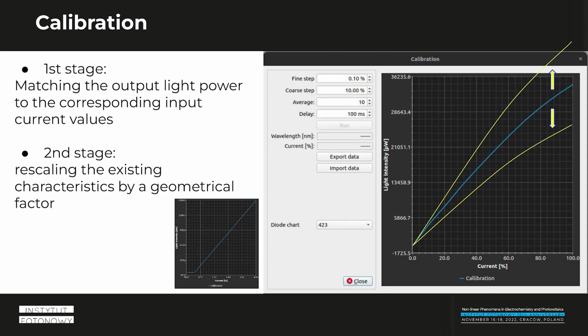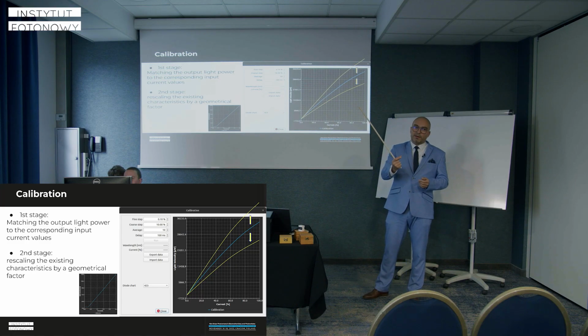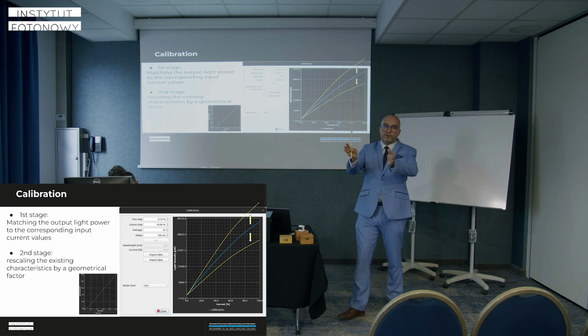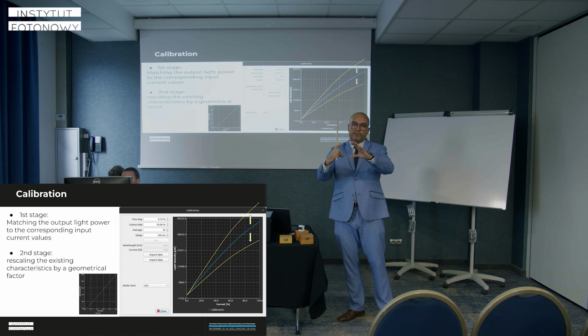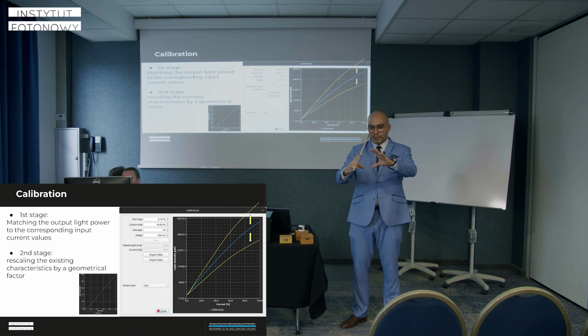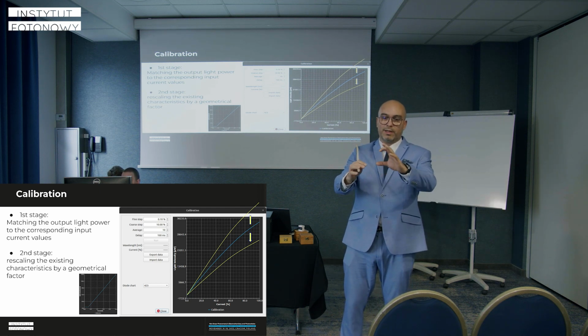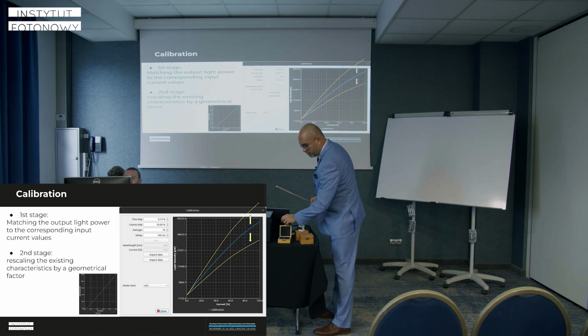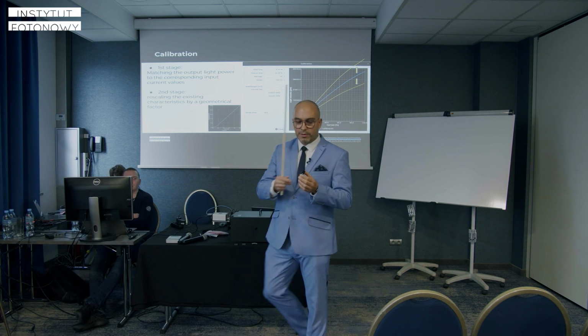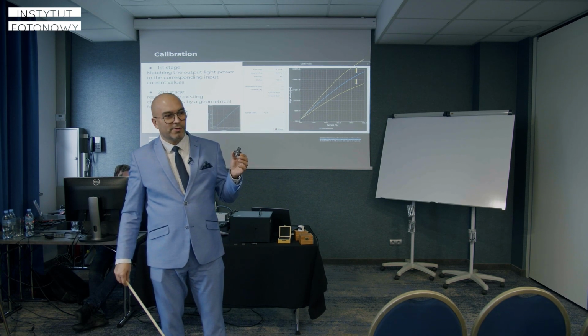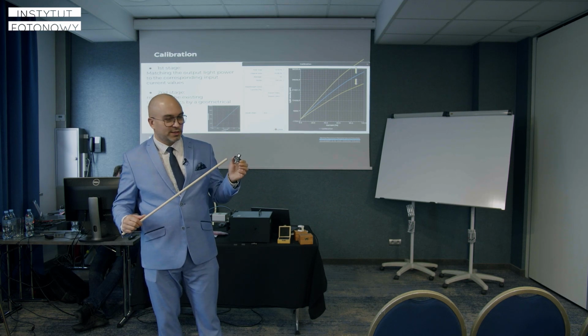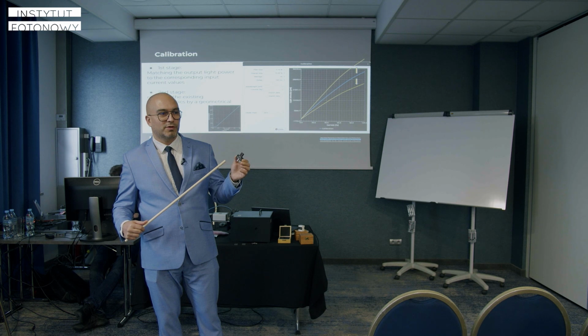And the second stage of calibration is when we change the geometry of our measurement, because if we move the sample closer or farther from the light source, there is a cone of light from the LED with a lens we focus. We take some of the light of this cone in our lens, and then some light we focus on the sample and some light reaches our calibrator. We use a silicon photodiode as the measurement head of our calibrator with an area of 1 square centimeter. So the light power which is measured by the photodiode is in microwatts, and at the same time we can express it as milli or microwatts per square centimeter.